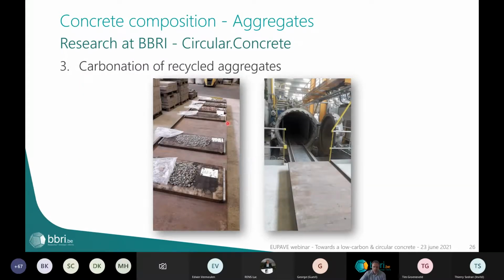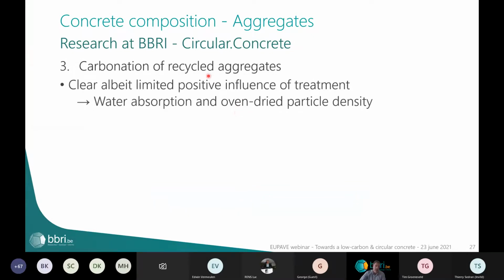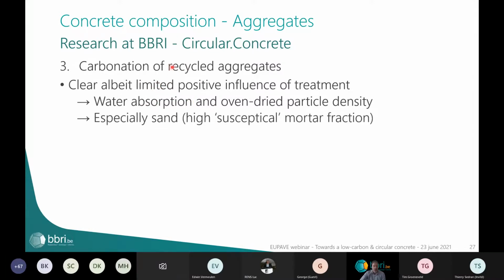So we did these experiments. We used an autoclave in which 100% CO2 was injected into the aggregates at high pressure, and we looked at the differences, and we could see that it has a positive influence. We looked at the water absorption and the particle density of the aggregates, and they showed improvements. But it was very limited. The highest positive influence could be seen in the sand fraction, and this is logical because the sand consists mainly of mortar, so it can be carbonated at a higher rate than the coarse aggregates.